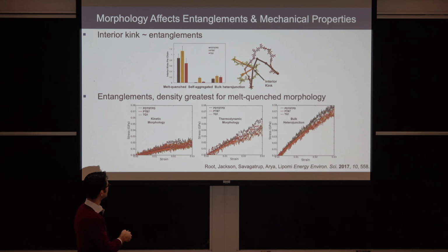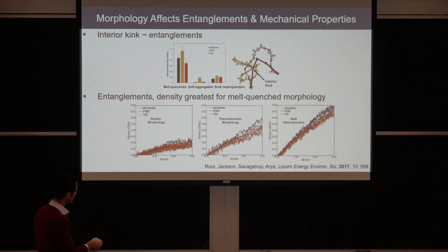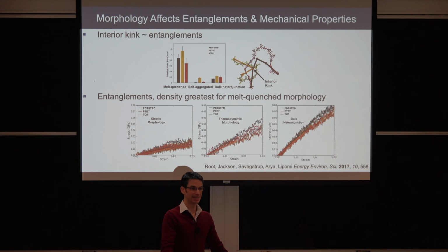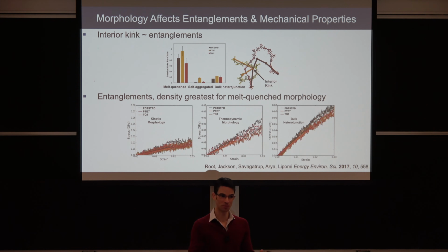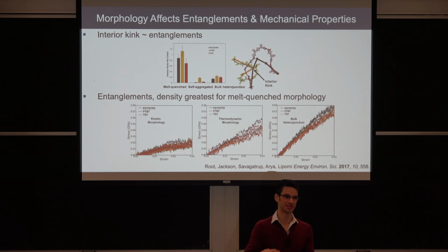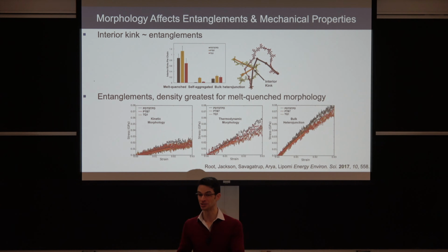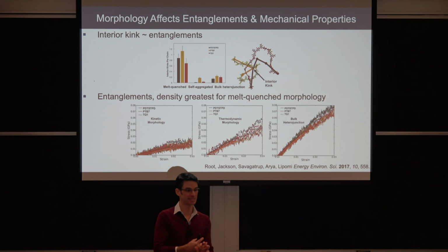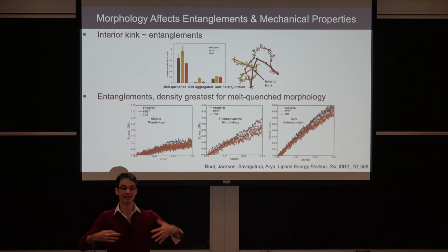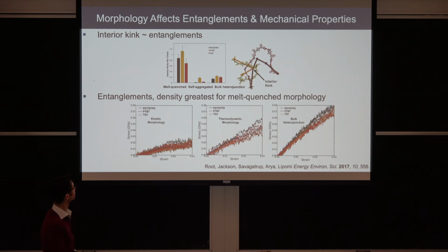And what that leads to is that in the melt-quenched, which is actually this morphology. Forget the word thermodynamic and kinetic. This is the melt quenched. This is the self-aggregated morphology. We can see that the materials actually behave relatively similar. So the way that you process the film is quite important, and perhaps even more important than the molecular structure, assuming that they all have similar solubility properties, which they don't. So the molecular structure is important, but the way in which you process the film, to a large extent, because of these nanoscale phenomena, really determine the properties that you get overall.